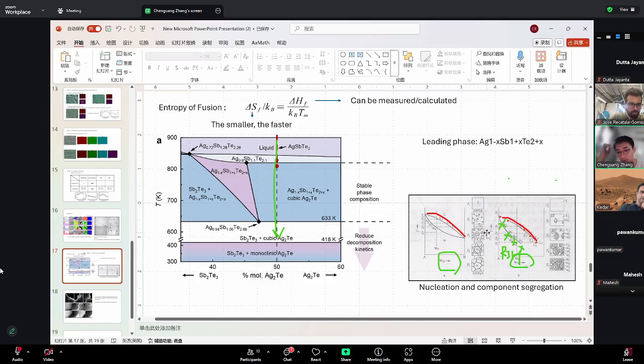No, there is no absolute equilibrium solidification process, right? It's just a comparison. If you have a very slow cooling, then you show the left picture. If you have a very fast cooling, then you show the right picture. But you can never get the absolute equilibrium process. The question is whether anybody has done this sort of experiment. Have you seen any evidence, even in the reference that Pepe has sent or others, of cooling rate controlling the phase fractions?